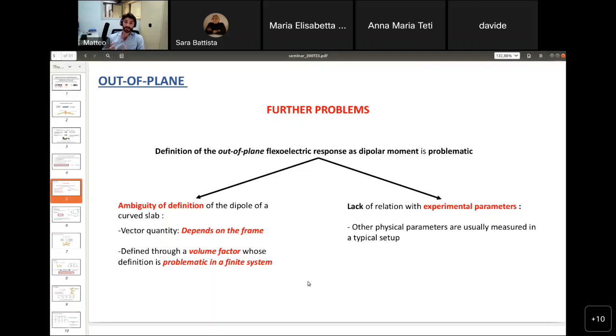Secondly, in the definition of the polarization, there is a volume factor, and this is problematic because how can you properly define, for example, the thickness and consequently the volume factor in the case of a two-dimensional material? How can you decide how thick the material is? In fact, if we try to apply the definition of the polarization and try to describe the flexoelectric response by use of the polarization, this turns out to be ill-defined.